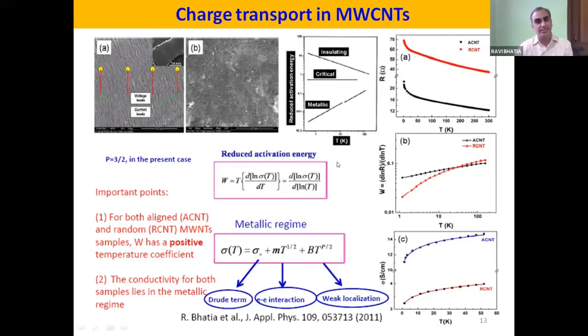The reduced activation energy is a term introduced by Zabrodskii in 1985, in which the conductivity versus temperature is converted in terms of reduced activation energy, W equals d ln sigma by d ln T. If you plot this W versus T on a log plot, the metallic situation shows that W should have a positive temperature coefficient, and if it is insulating, that means there is a large change in the resistance from 300 Kelvin to 1.5 Kelvin. It shows insulating behavior, and the metal insulator boundary is seen when W versus T on the log plot is independent of temperature, that is the critical regime.